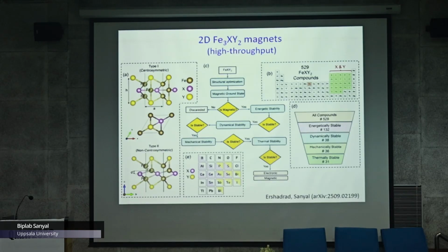And as I said, iron 3 germanium telluride. So our first idea was that if you replace germanium and tellurium by this block from the periodic table, then what happens? When you have so many different compounds, you have to study certain stability criteria. This is not a complete condition for stability, but nevertheless we look into some entropic and enthalpy considerations. So phonon calculations, dynamical stability, mechanical stability, and also thermal stability at high temperature, whether they're stable or not. So from 529 compounds, we came to around 31 stable compounds.